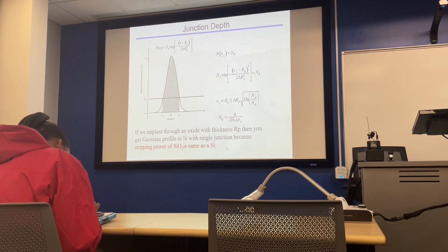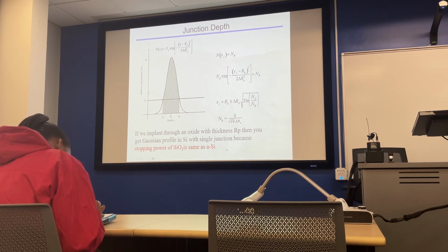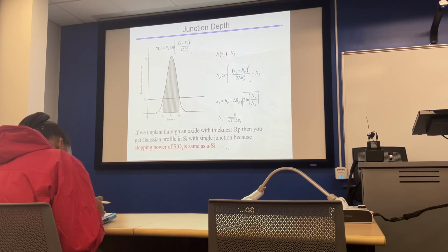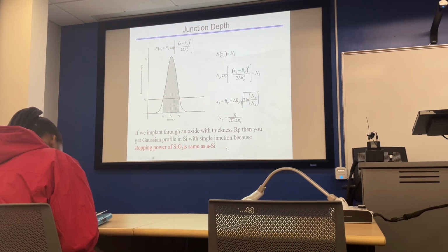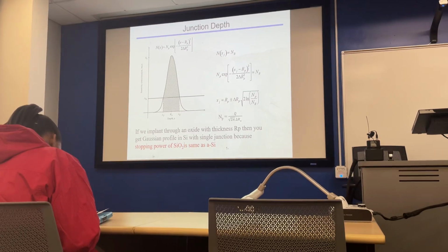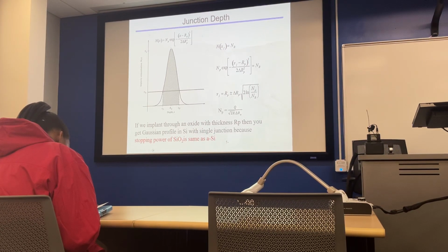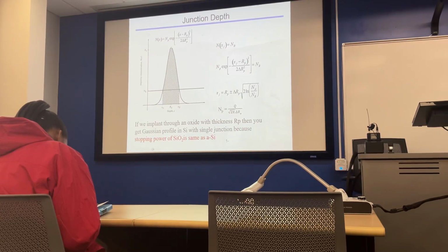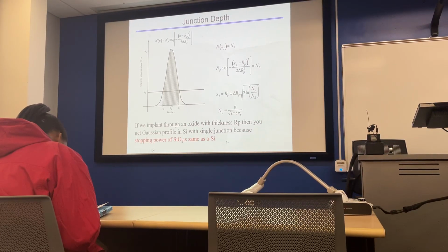Or you could sometimes want the reverse, because sometimes in the channel implant, you want a very low surface concentration. So you will make this one short. So you can do many things, but mathematically also, can you understand? Because if I wanted to just get a taller peak, I have no problem. My dose will be higher, but the profile will remain Gaussian, right? And my peak will change a little bit. Now Rp will be changing if I did it by energy, right? My Rp will change.